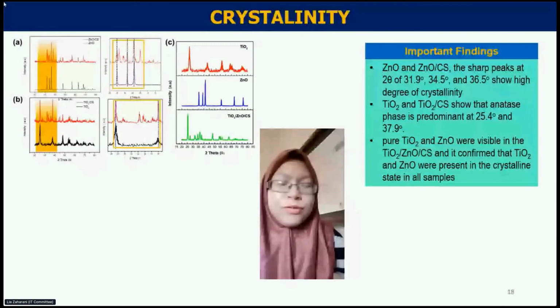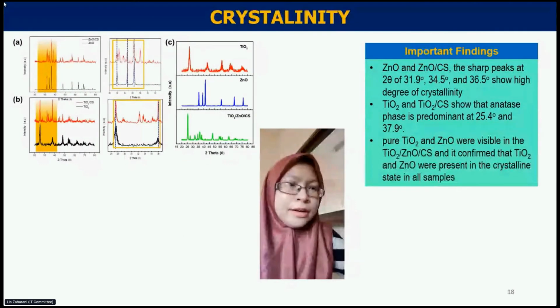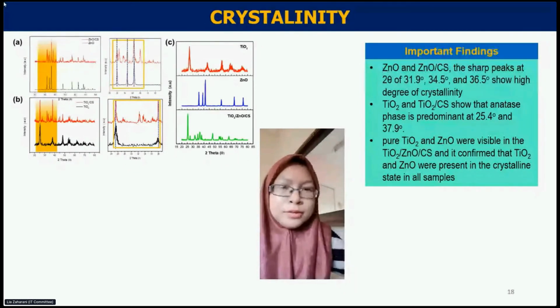For the crystallinity analysis, it shows that the anatase phase is predominant for the hybrid systems. The XRD peaks of the pure TiO2 and zinc oxide also become visible in the hybrid system, and this confirms that both of the metal oxides, TiO2 and zinc oxide, were present in the crystalline state in all the samples. The result was also consistent with what was found in the literature and suggested that some change occurs due to the hydrogen bonding with the chitosan group.